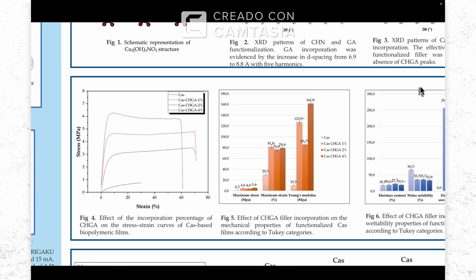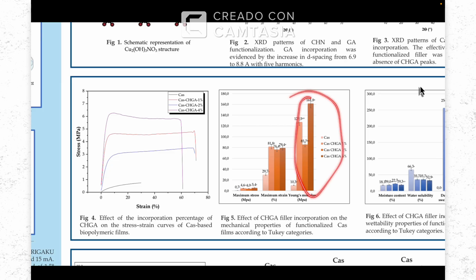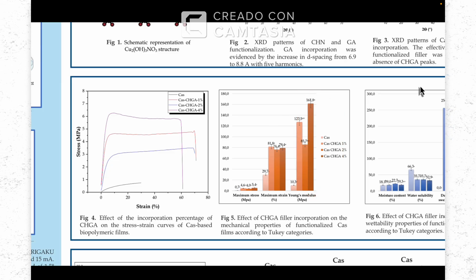In figures 4 and 5, we can observe a significant increase in the mechanical properties, particularly with the films that have concentrations of the functionalized material at 1% and 4% when we compare with the original calcium caseinate film. The Young modulus also shows a significant increase.